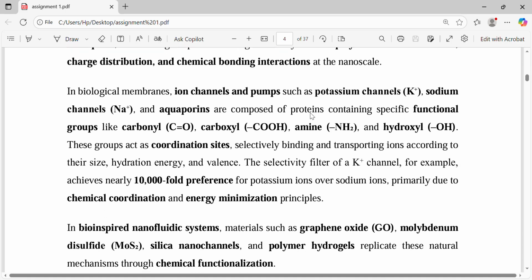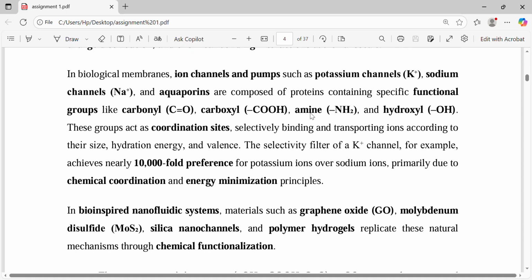In biological membranes, ion channels and pumps such as potassium channels and sodium channels are composed of proteins containing specific functional groups like carbonyl, carboxyl, amine, and hydroxyl. These groups act as coordination sites, selectively binding and transporting ions according to their size, hydration energy, and valence. The selectivity filter of the potassium channel, for example, achieves nearly 10,000-fold preference of potassium ions over sodium ions, primarily due to chemical coordination and energy minimization principles.